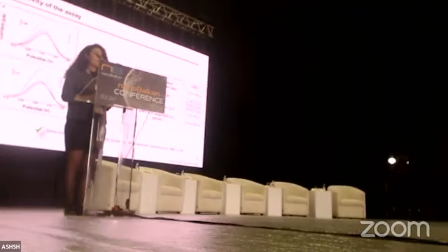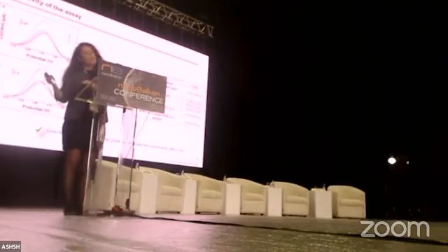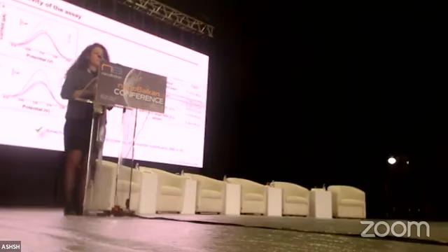And next, the selectivity of the assay was tested in the presence of non-complementary and mismatch sequences, which have only one base difference from the target sequence. And also we tested our selectivity in the presence of mixture samples, which contain both target and non-complementary, or target and mismatch sequences in a 1:1 ratio. In the case of full hybridization with our target microRNA, we had the lowest signal, and we can say selective behavior is obtained even in the presence of unwanted sequences.